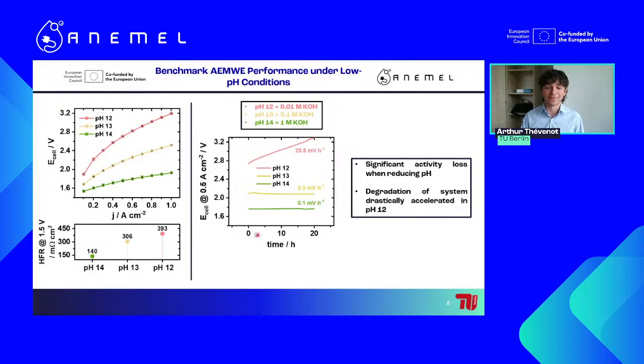Now we tried to do a stability test afterwards. I mean, if we may call it a stability test, as it's only 20 hours. And we saw that for the pH 14 and the pH 13 tests, we still had, I would say, reasonable performance loss after 20 hours. But for the pH 12, we have an enormous 25.8 millivolt per hour, which is gigantic. I mean, you can just discard it at that point, you know. So this raises the need to optimize the system to go lower in pH.